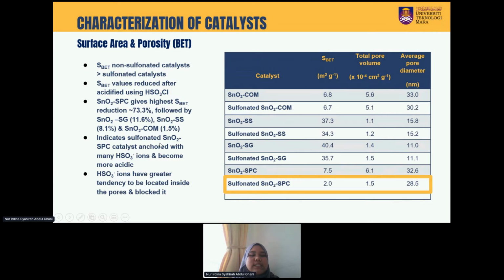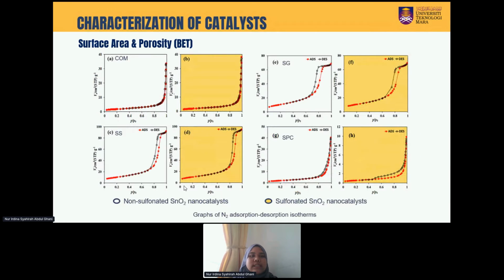This also indicates that the sulfonated tin oxide SPC catalyst is anchored with many sulfonic ions and becomes more acidic. The sulfonic ions have a greater tendency to be located inside the pores and block them. So this is the surface area and porosity from the BET.